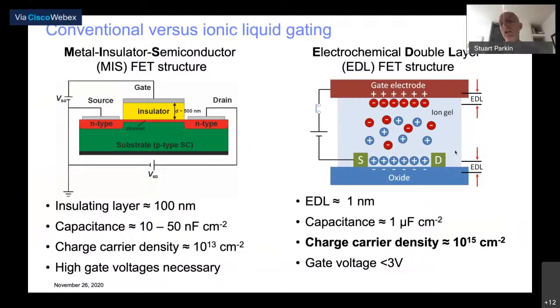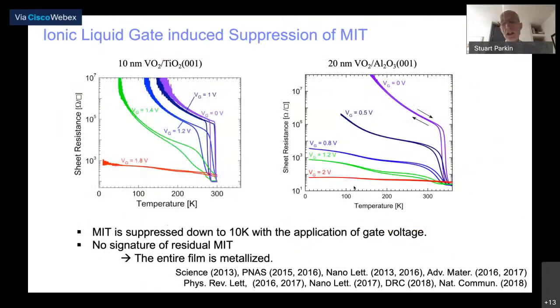You apply a gate voltage and you cause an accumulation of charged molecules of one type at the surface of a channel. Shown here, positively charged molecules at an oxide surface. And we discovered a few years ago that these electric fields are so great that they cause oxygen to leave the oxide. And this can cause dramatic changes in properties. One of the ones we looked at was vanadium dioxide, which is an archetypical Mott insulator, which is metallic above 300 degrees and becomes an insulator at low temperatures through a metal to insulator transition. And we showed by ionic liquid gating, we could completely suppress the insulating state shown on the left. The purple curve shows a fantastic insulator, the red curve shows after this ionic liquid gating, it remains metallic